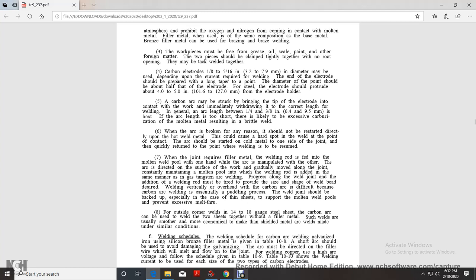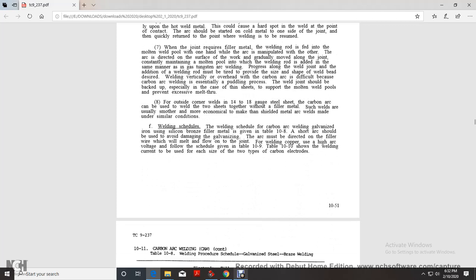The addition of the welding rod must be timed to provide the size and shape of the weld metal bead desired. Welding vertically or overhead with the carbon arc is difficult because carbon arc welding is essentially a puddling process. Welding joints should be backed up, especially in the case of thin sheets, to support the molten weld pool and prevent excessive melt-through. For outside corner welds on 14 to 18 gauge steel sheet, the carbon arc can be used to weld two sheets together without filler metal. Such welds are usually smoother and more economical to make than shielded metal arc welds made under similar conditions.